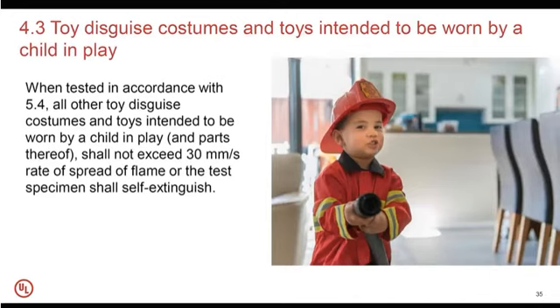For this chapter, when tested in accordance with 5.4, all other toy disguised costumes and toys intended to be worn by a child in play and part thereof shall not exceed 30 millimeter per second rate of spread of flame, or the test specimens shall self-extinguish. So this is for the requirements. Then let's see the test methods.